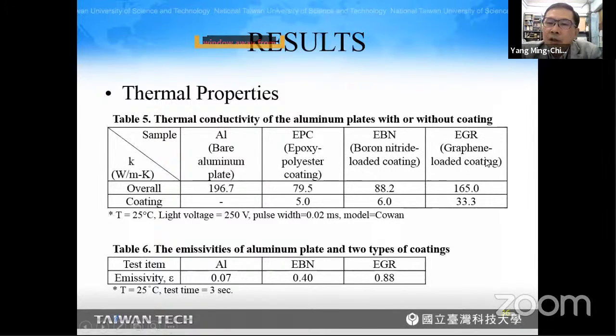And for graphene loaded coating, the total thermal conductivity increased to 165. Among this, the conductivity of the coating provided 33.3 watts per meter per Kelvin. And this table shows the emissivities of aluminum plate and two types of coatings. For the aluminum plate, the emissivity is only 0.07. For boron nitride loaded coating, it is 0.40. And for graphene loaded coating, it is 0.88.